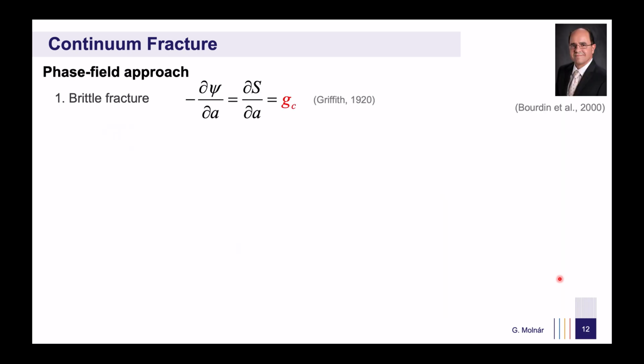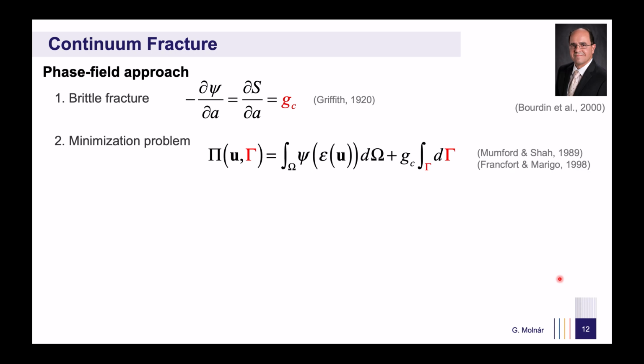Bourdin's approach was based on Griffith's original criterion, which states that a certain amount of energy is required to create a new crack surface. To advance this idea, he used the variational formulation of Francfort and Marigo, which determines the size of the new crack based on an energy minimization principle. However, in their original work, the crack surface gamma was still treated as a discrete quantity.